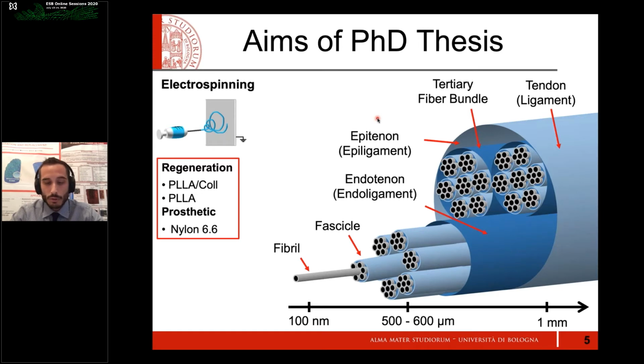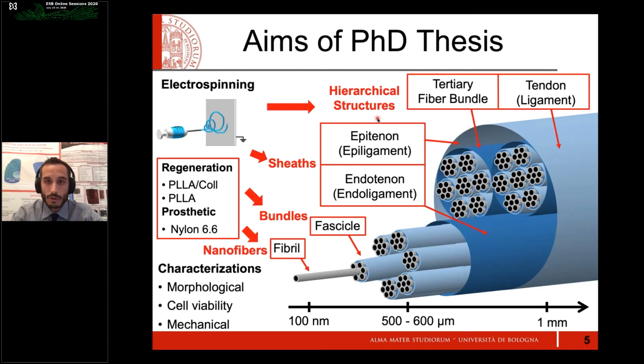And then to try to use these nanofibers to reproduce the whole hierarchical structure and mechanical properties of tendons and ligaments, starting from the fibrils of collagen with our polymeric nanofibers, passing to the fascicles using electrospun bundles, and then grouping several bundles together with an electrospun sheath able to mimic the epitenon, epiligament, or the endotenon, endoligament tissue, reproducing so the tertiary fiber bundles or the whole tendon and ligament tissue. And then, of course, to characterize them from the morphological, cell viability, and mechanical points of view.